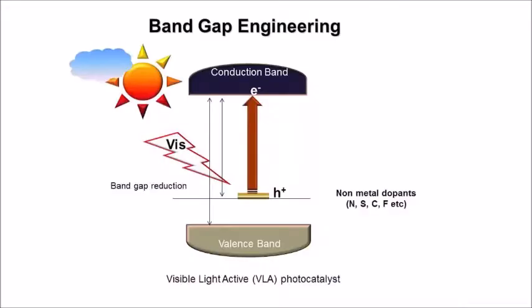For example, in the case of anatase TiO2, the band gap is 3.2 electron volt. This means that photons of light in the ultraviolet region only can initiate the photocatalysis reaction. As we know, ultraviolet light makes up approximately 5% of the solar spectrum, whereas almost 40% of the solar photons are in the visible region. Therefore, in order to enhance the efficiency of TiO2 under solar irradiation, it is necessary to modify the band gap to facilitate visible light absorption.